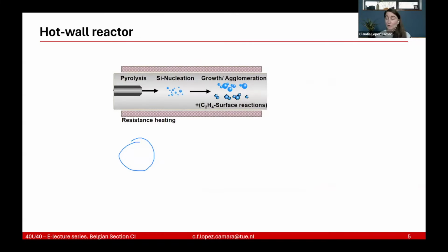Then we also have hot wall reactors. Let me see if I can erase this thing, one second. Good, perfect. So yeah, we also have hot wall reactors, which are another way of gas phase synthesis. In the hot wall reactor, you can imagine that you have a cylinder, a ceramic cylinder, with a resistance heating it on the outside. And inside you have a nozzle, which is shown here on the left. From the nozzle you get your precursor into your hot wall reactor, and then it nucleates and grows, as I mentioned in the very first slide.